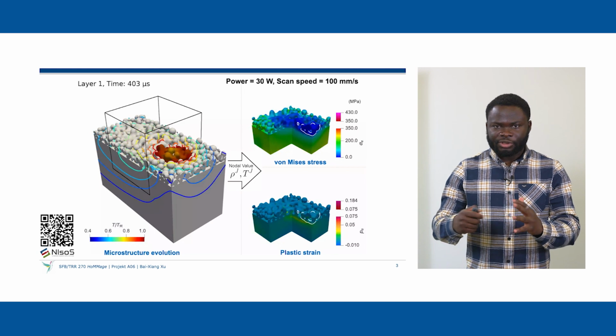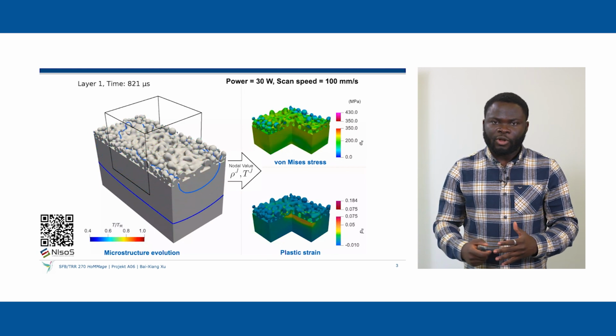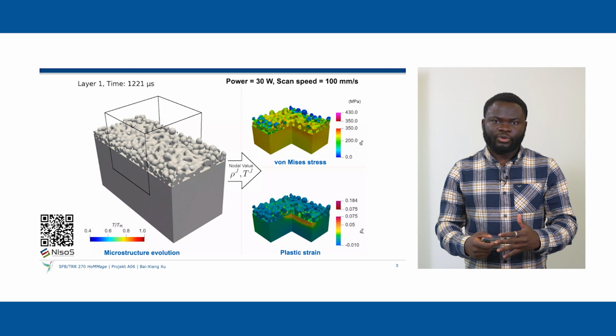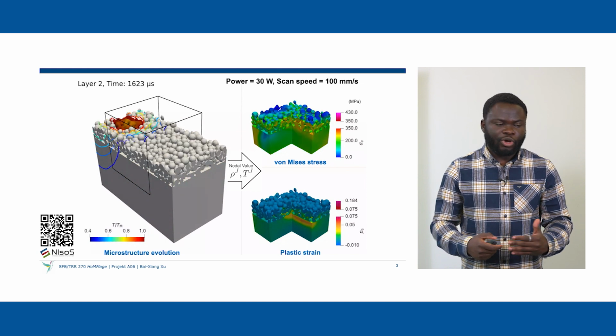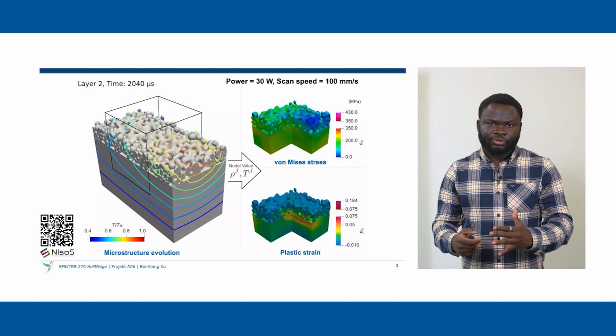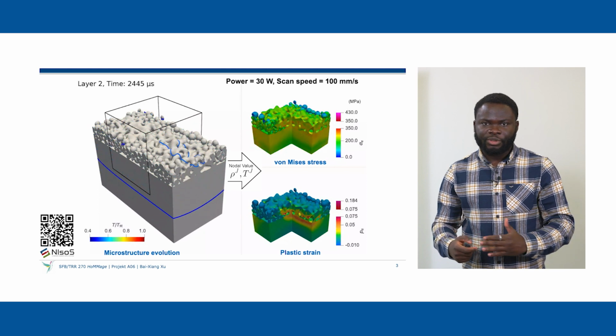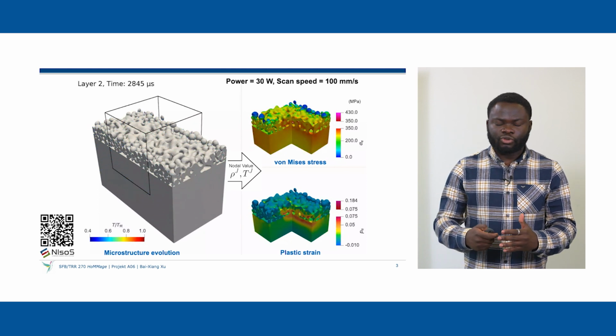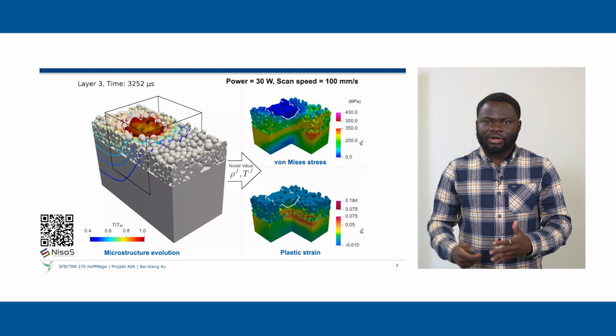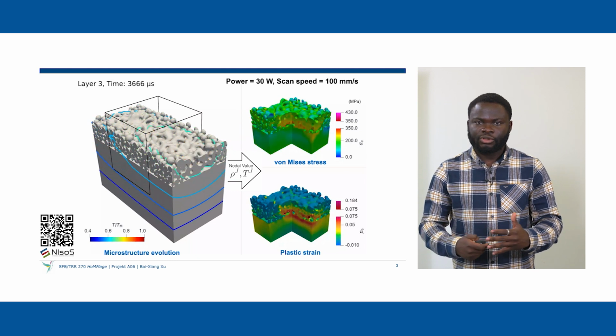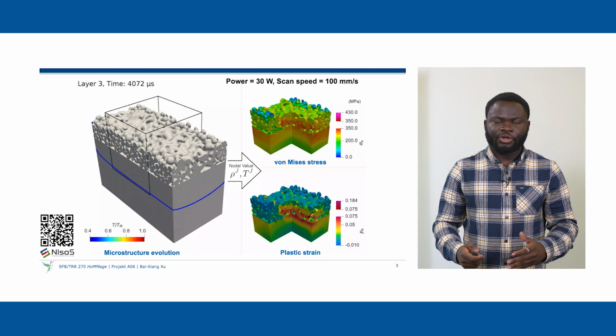Lastly, I show you a simulation example of what we do, where I show a multi-layer build-up of an iron-based alloy, where you have the layer build-up of the materials and also the movement of the laser beam. On one side, I also show the build-up of the plastic strain and also the build-up of the residual stress during this layer-by-layer build-up. Thank you.